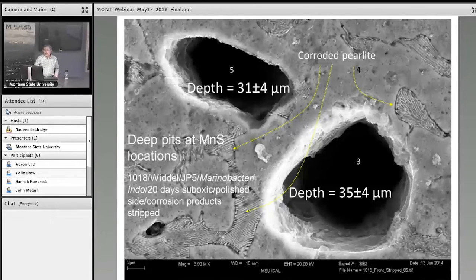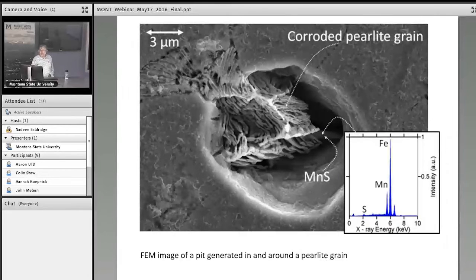So a couple of other tricks that I would like to mention here. Whenever there's strain, this is our pearlite feature, it's corroded away, and it starts digging a hole. And suddenly, this is the surface polished parallel. So manganese sulfide stringers are running underneath the surface, parallel to the surface. Here, we unearthed a manganese sulfide inclusion, and the hole is following into the material along the manganese sulfide inclusion.